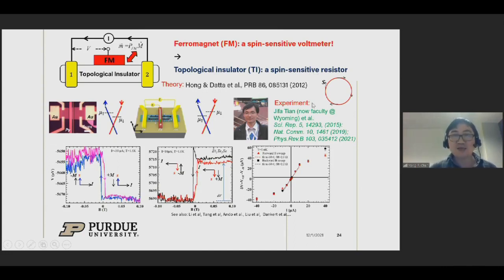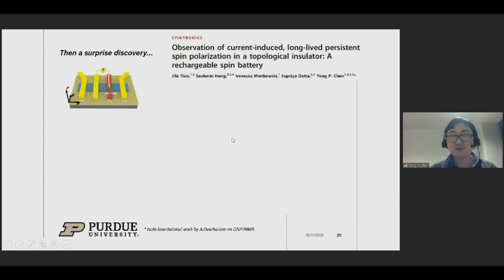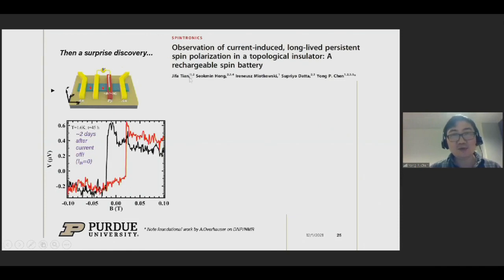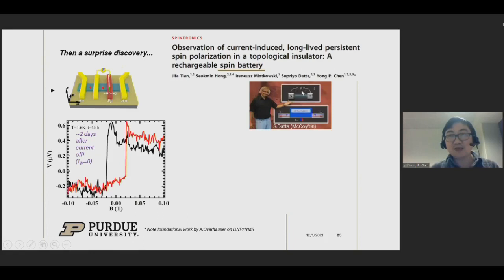But there's more. A somewhat surprising discovery is that after performing this measurement for quite a bit of time, even after removing the current, our former postdoc Jifa Tian discovered that the voltage measured by this spin-sensitive voltmeter, namely the ferromagnet, actually maintains a voltage that stays for a very long time, even after removing the current. And our colleague Supriyo Datta noticed this: something with a voltage output, right? Even without current, it's basically a battery. So we now call this a spin battery, because it's measured by a spin-sensitive voltmeter, namely the ferromagnet.